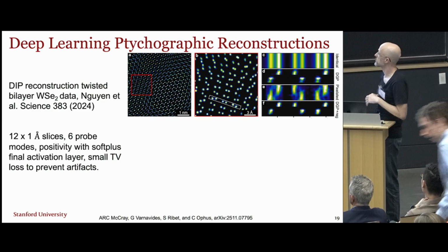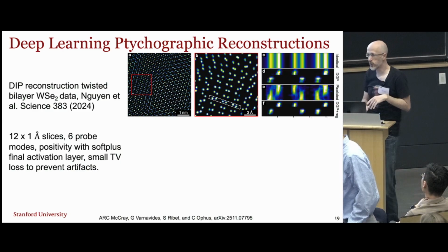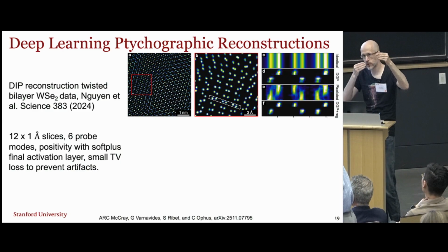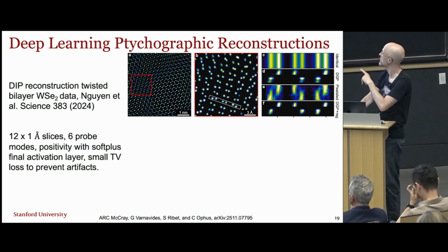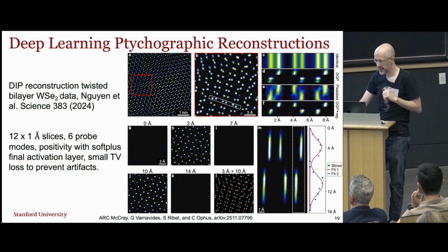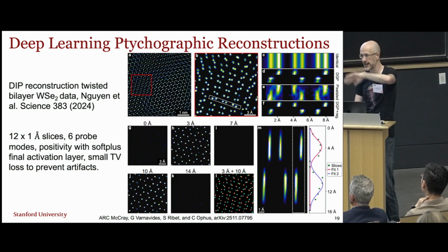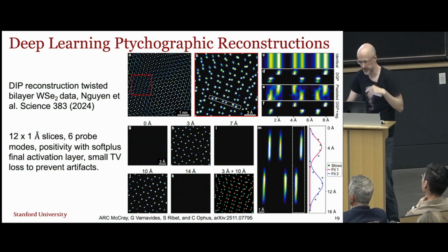But this is another reason why we really like these deep priors. Without any additional tuning, they recover almost the ideal 1 nanometer or 10 angstrom resolution along the beam. And if you apply a little bit of positivity and softplus regularization, you get nice sharp atoms. And we're fitting it and hitting about that 10 angstrom or 1 nanometer theoretical limit here. So able to separate out the 2 layers of that twisted bilayer.